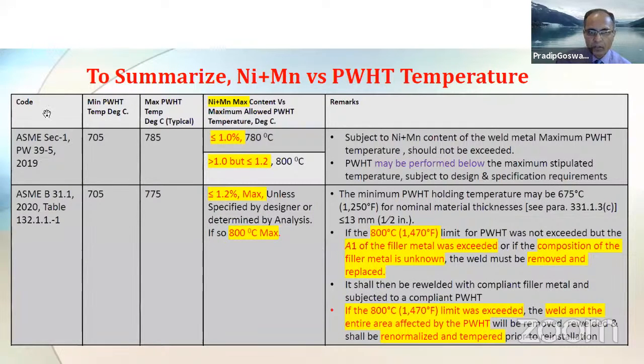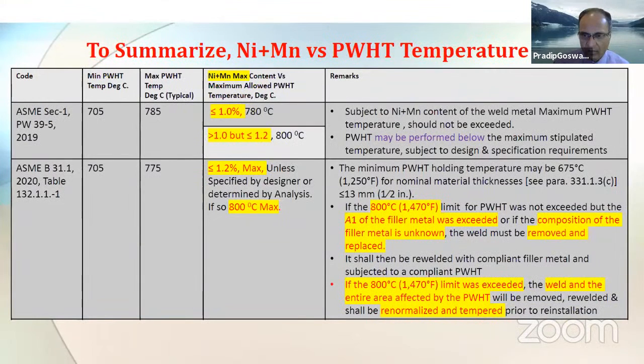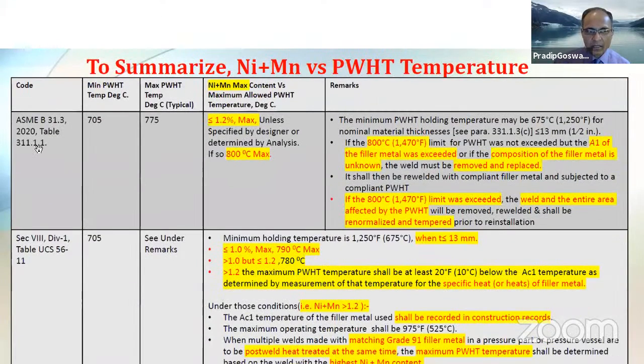As you see on the spreadsheet, you see the code, minimum post-weld heat treatment, maximum, and nickel plus manganese, how much should be allowed. And this is for Section 1, B31.1. You are able to see for yourself what the typical minimum and maximum post-weld heat treatment temperatures are, and what the nickel plus manganese content is, which is allowed by the individual section of these codes. And same here is B31.3. This table is for B31.3 and ASME Section 8 Div 1.